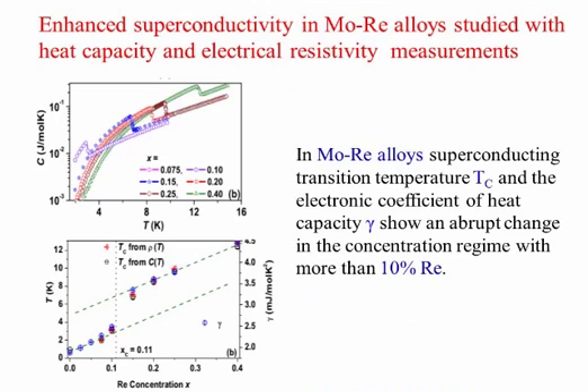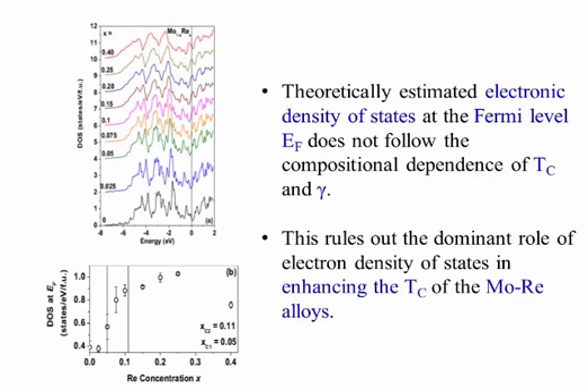In the present paper, we build on this recent work and address this unresolved issue of the enhanced superconductivity in molybdenum-rhenium alloys. First of all, we find that in these alloys, the superconducting transition temperature TC and the coefficient of the electronic contribution to the heat capacity, gamma, show an abrupt change in the concentration regime with more than 10% rhenium. Theoretically estimated electronic density of states at the Fermi level does not follow the compositional dependence of TC and gamma. This rules out the dominant role of density of states in enhancing the TC of the molybdenum-rhenium alloys.